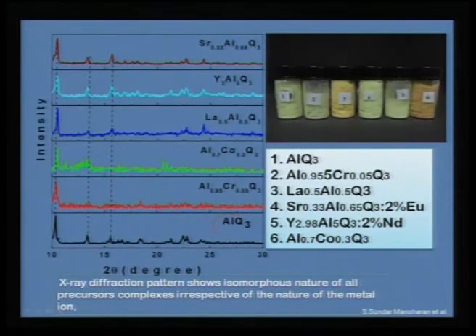As you could see here, AlQ3 has a typical X-ray pattern like this, where you have a very strong peak somewhere around 10 degrees, and if I am going to put 5% of chromium in this AlQ3, you can see that the crystal structure absolutely remains the same. Now, I can go to another situation where I put 30% of cobalt there, and you would see that the AlQ3 structure is still retained, or if I put 50% of lanthanum, still this crystal structure is retained, or you can go for any other variation. In all these cases, you would see that the AlQ3 X-ray structure is retained. Therefore, I can call all of these solid solutions